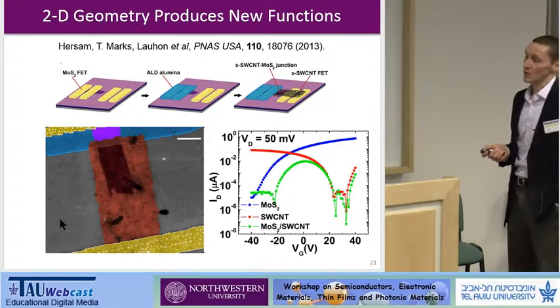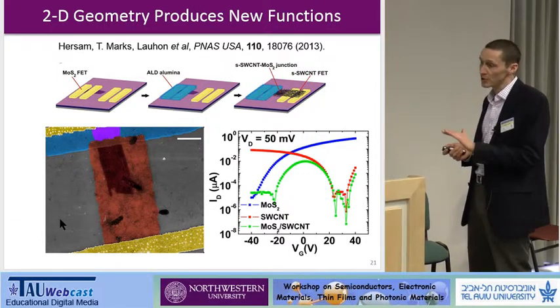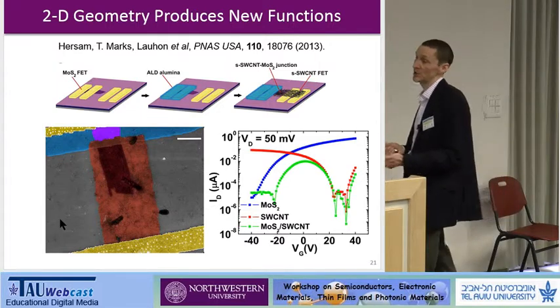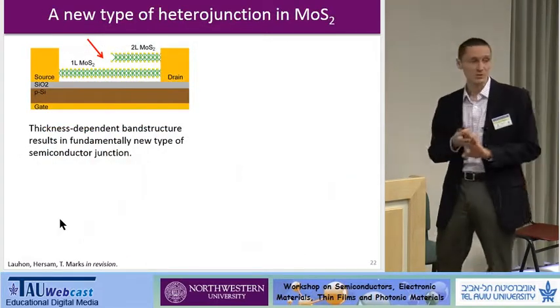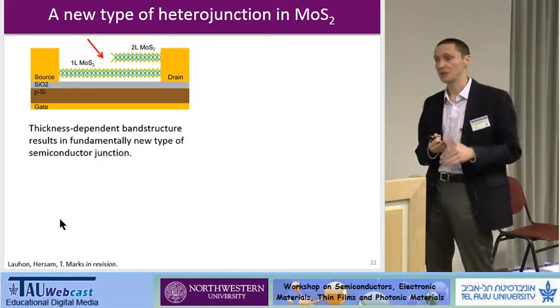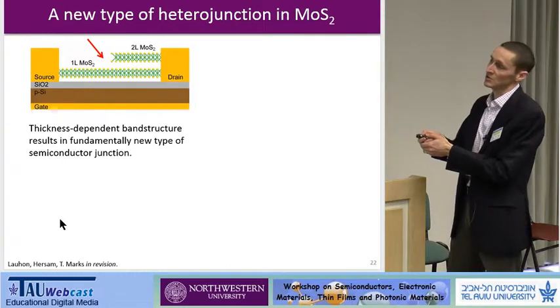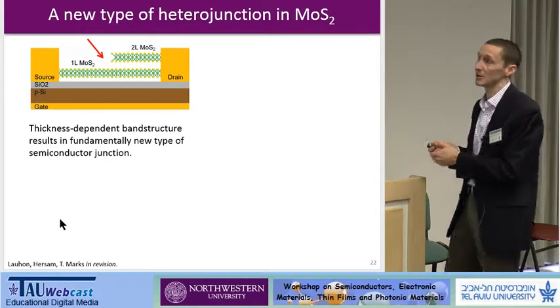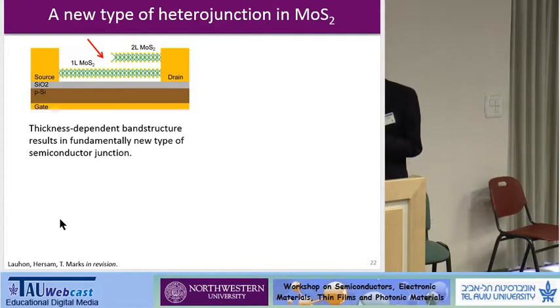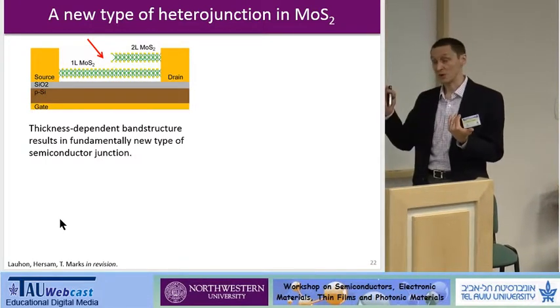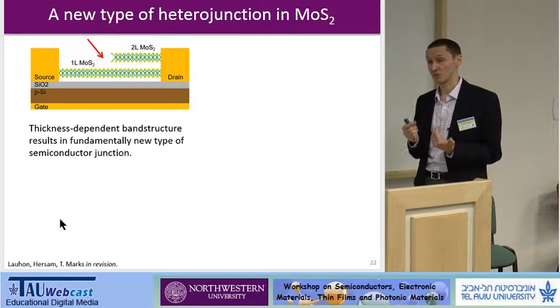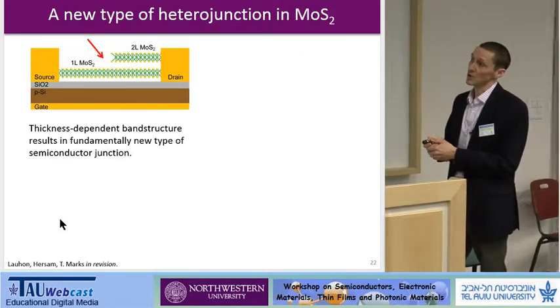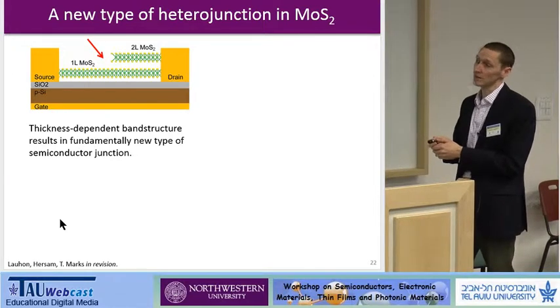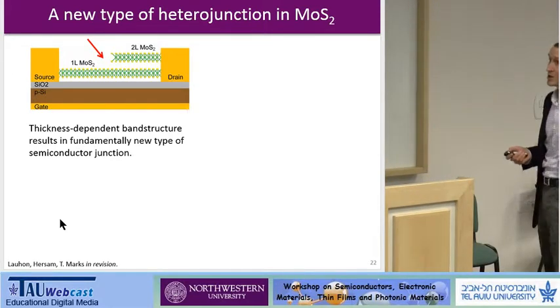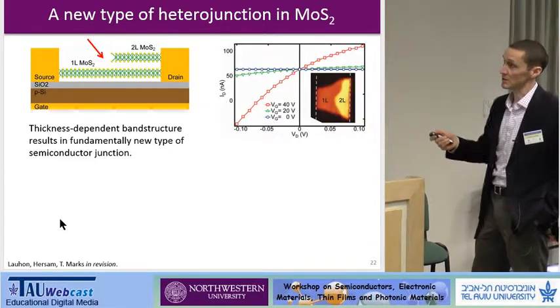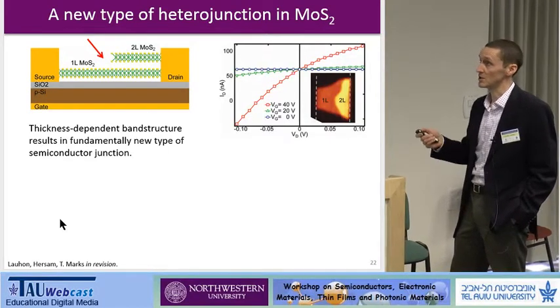So I'm going to talk about not this vertical junction, but another kind of unique lateral heterojunction that occurs when you do this Scotch tape method of exfoliation and sticking down 2D materials. You find that sometimes you get a transition between a monolayer and a bilayer. Now, if you've seen these plots or heard how the band structure evolves as you make MoS2 thinner and thinner, and in fact it goes from an indirect to a direct gap, you could ask yourself, well, if this is an indirect gap semiconductor and that's direct, what kind of junction do we have? Okay. So if you put contacts on such a device, as in here between a 1-layer and a 2-layer device, you see that it's rectifying.